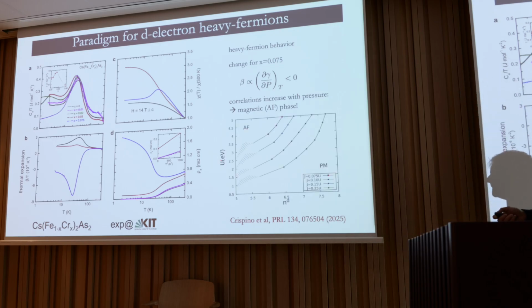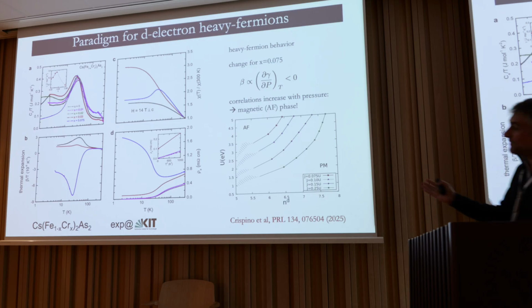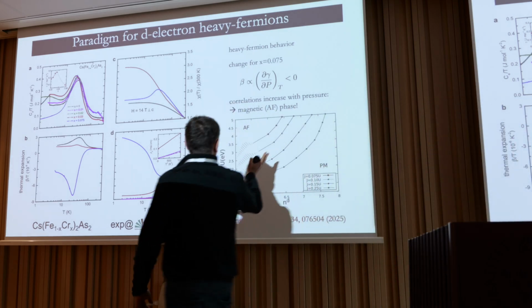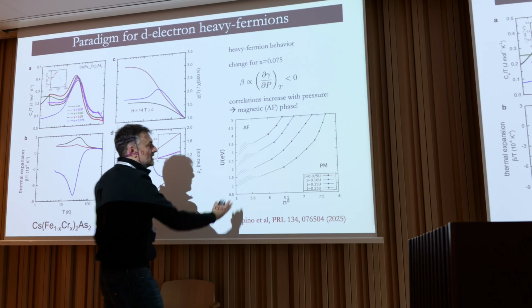And we do calculations also of the magnetic phases, and indeed we always find, as a function of doping, that you enter an antiferromagnetic phase. This depends on the details of the parameters, which are not realistic, but it's always a phase that you find at large interaction and near half filling.